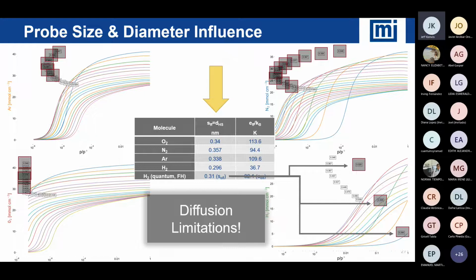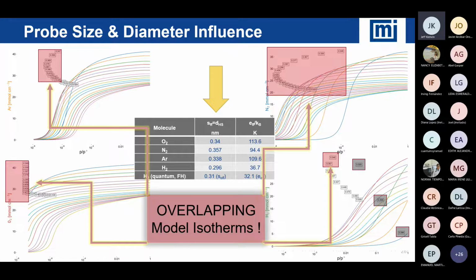So when we perform modeling, we can calculate adsorption that may be in sizes that are ultimately diffusion limited. So we could look at adsorption of oxygen in a pore nearly at 0.34 nanometers, the size of the oxygen molecule. Experimentally, we may not observe that adsorption, and it's a diffusion limitation. Down below with the hydrogen, we really pointed out that there is adsorption in pores with hydrogen. Hydrogen cannot get into those pores because of the size, right? Likewise for nitrogen, upper right, likewise for argon or oxygen. So there are experimental diffusion limitations that we always have to be aware of that can complicate modeling, and it can complicate our interpretation.